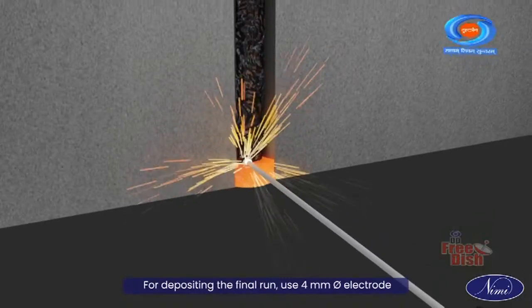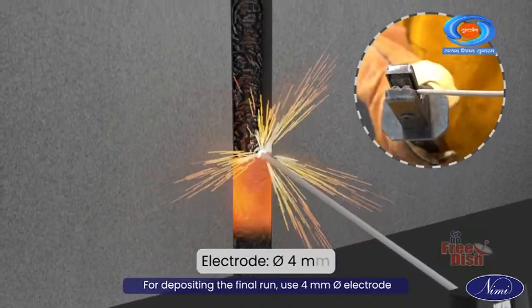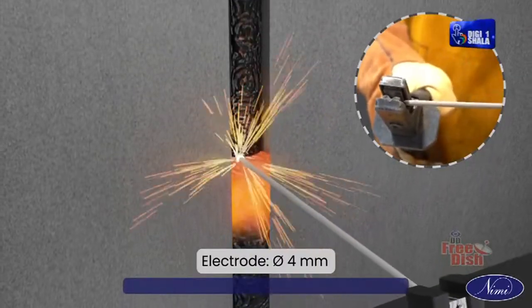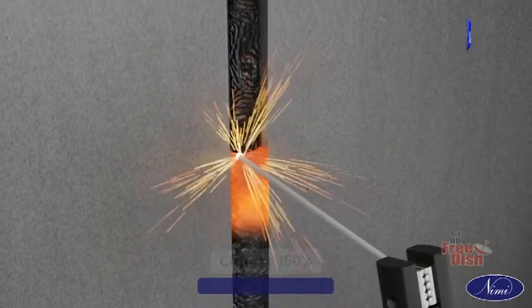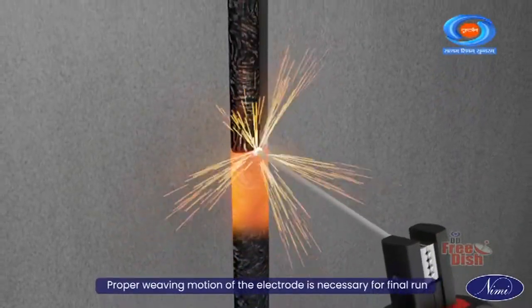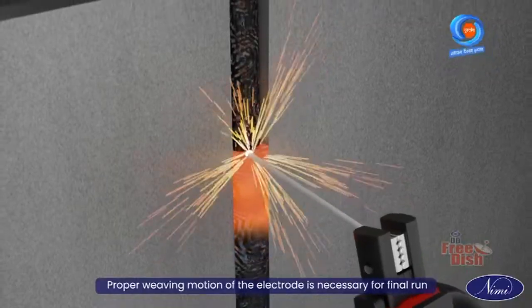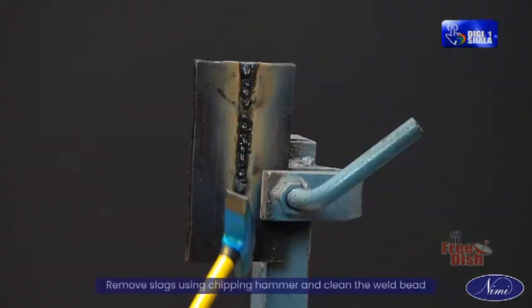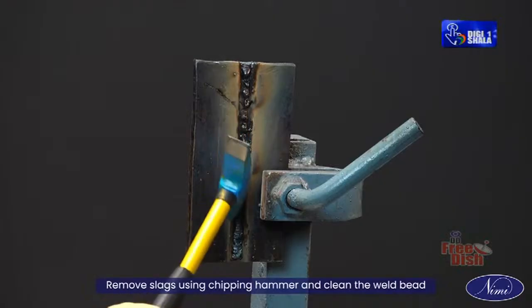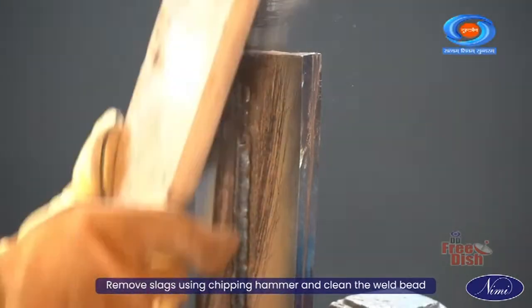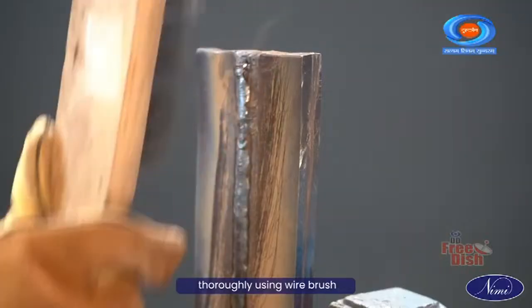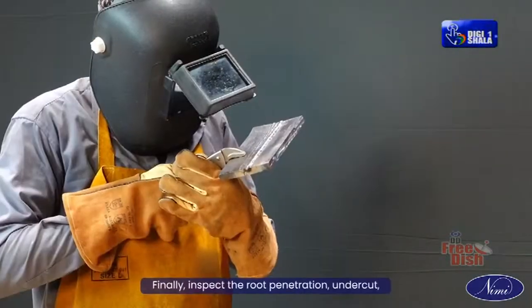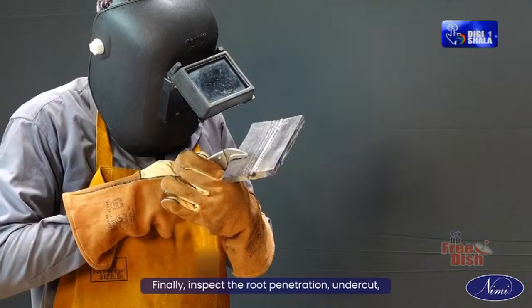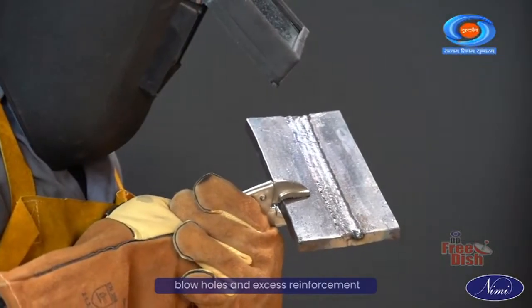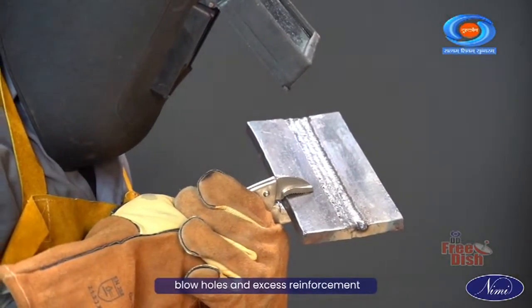For depositing the final run, use 4 mm diameter electrode and 150 ampere of current. Proper weaving motion of the electrode is necessary for final run. Remove slags using chipping hammer and clean the weld bead thoroughly using wire brush. Finally, inspect the root penetration, undercut, blowholes and excess reinforcement.